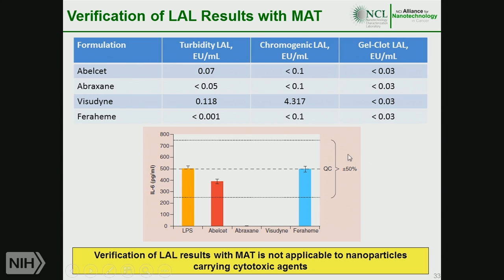This data can be verified by the monocyte activation test, but there is a nuance, and this nuance deals with the drug that these particles deliver. While Abelcet and Feraheme could be reliably retested in the monocyte activation test, and you see spike recovery is acceptable, Abraxane and Visudyne cannot be tested by this test because they contain a cytotoxic drug which kills the cells, and therefore the results are false negative.